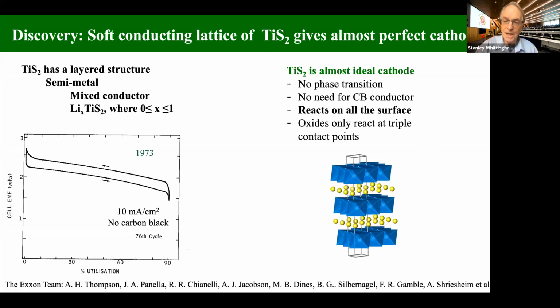And it turns out that it's about 1 or 2%. This is advantageous because it stops these sheets from moving relative to one another. The other big advantage of this particular material, for practical purposes, is that it shows metallic conductivity. So in a battery, you need to get electrons in and out as well as move lithium ions. So in this case, we do not need any carbon black to increase the conductivity.